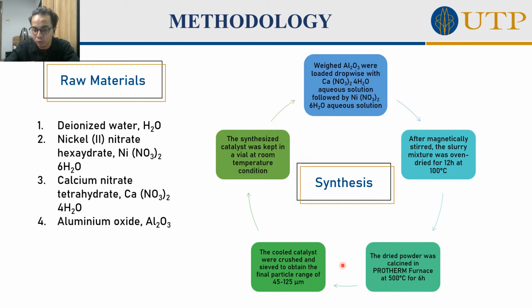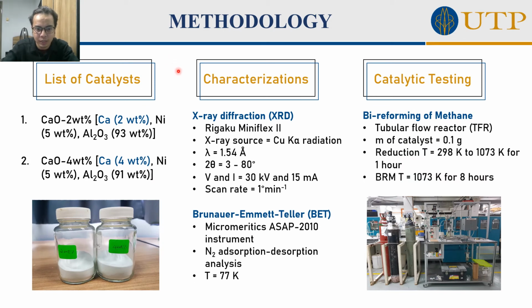After the calcination, we cooled down the powder, and the cooled catalyst was crushed and sieved to obtain a final particle range of 45 to 125 micrometers, and the synthesized catalyst was kept in a vial at room temperature. So next is the list of catalysts. This is the catalyst that I've synthesized for my project. The first one is CaO 2% and the next one is CaO 4%, with different weight percent of CaO, which is 2% and 4%. This is the picture of the catalyst that I have synthesized.